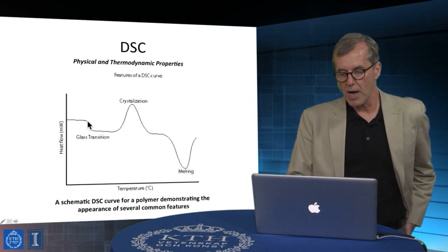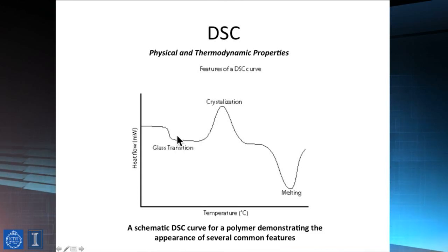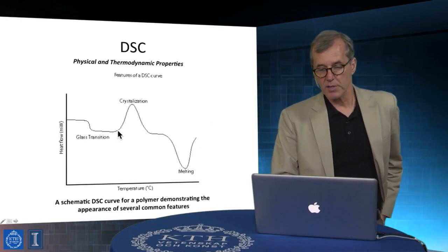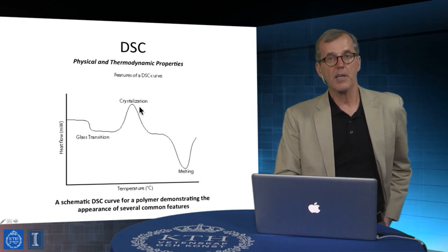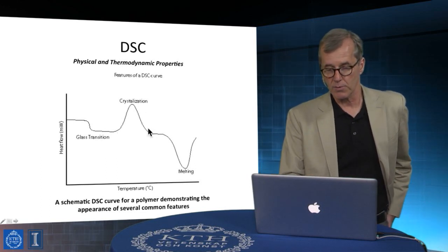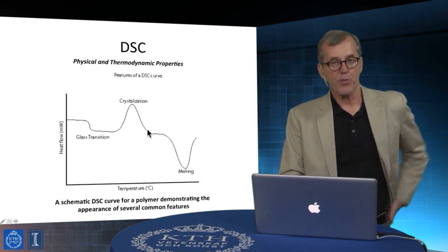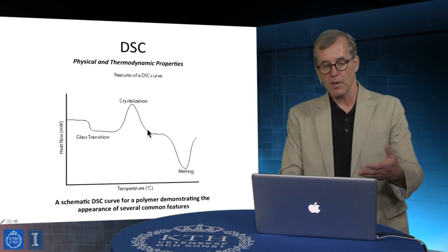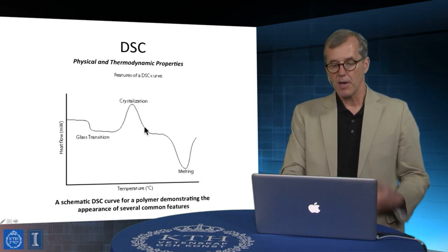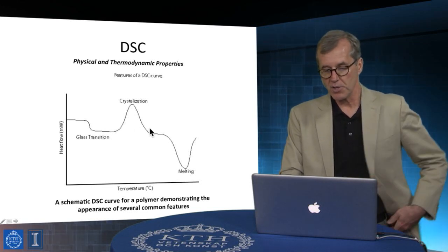The glass transition, the onset of molecular mobility, would be characterized by an endothermic heat flow. I run the sample temperature up, and I hit a temperature whereby, whatever the degree of crystallinity is in the sample, all of a sudden I get a spike that's due to an increase in that level of crystallinity, which is exothermic. So what you're seeing is the heat of fusion being liberated by this onset of increased crystallization in the sample.